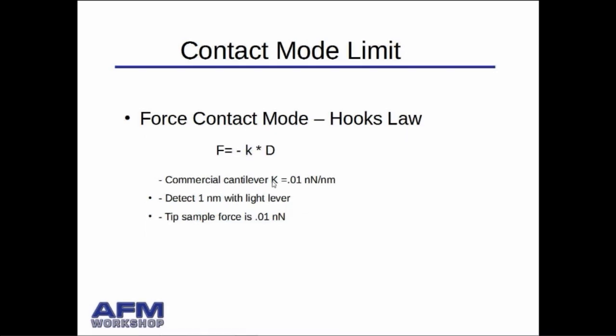So for a commercial cantilever, you can find force constants as low as 0.01 nanonewtons per nanometer. And typically, though, they're more like 0.1. But if you could detect a 1 nanometer change in the deflection of the cantilever with your light lever, then you can calculate very quickly that you can get a 0.01 nanonewton force measurement. And again, if you can detect a 0.1 nanometer motion of the cantilever, then you could get a 0.001 nanonewton. So that's kind of the limit. It's thousandth of a nanonewton using contact mode.